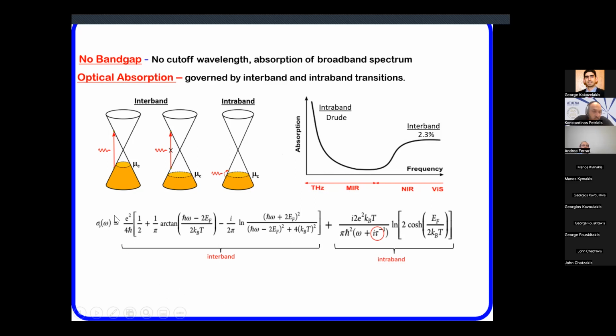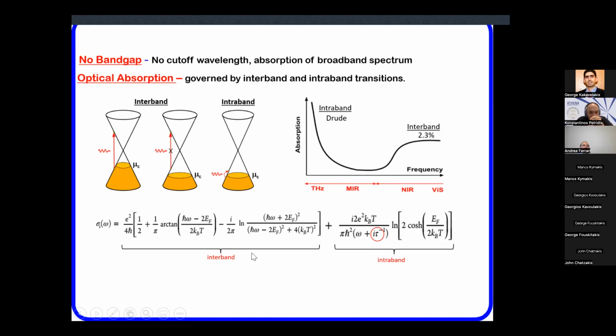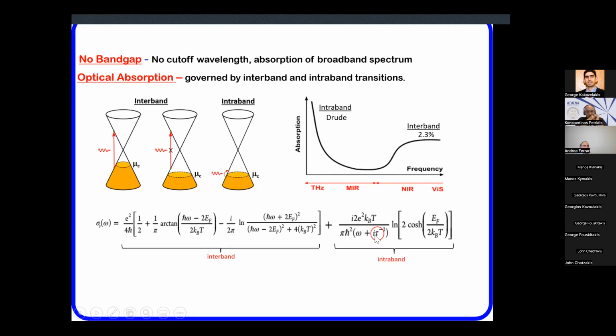And this describes the optical properties of graphene. There are lots of terms, but in reality, all of them are well known. There's the Fermi level here, there's the temperature, there is, of course, the energy we are looking at. But the most important term here for the intraband part is this tau, the scattering time. The scattering time is the only true definition of quality of a film of graphene. And this is directly related to the mobility.